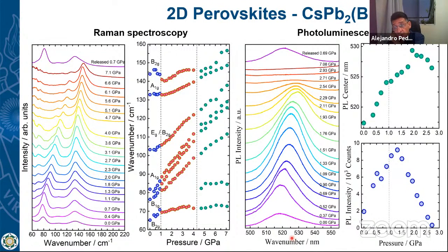Looking to the luminescence, it is very interesting. You are seeing the luminescence increase and later it decreases and goes to zero. So the pressure is quenching, is killing the luminescence, but it disappears before the second phase transition. So this process is not directly associated to a structural phase transition.